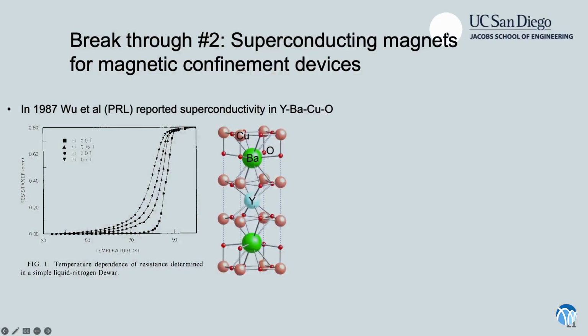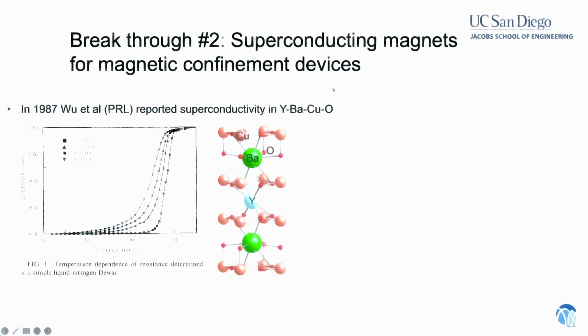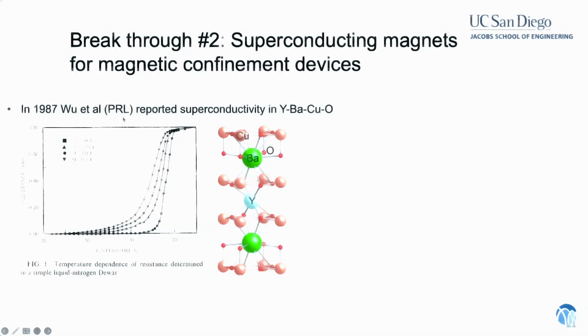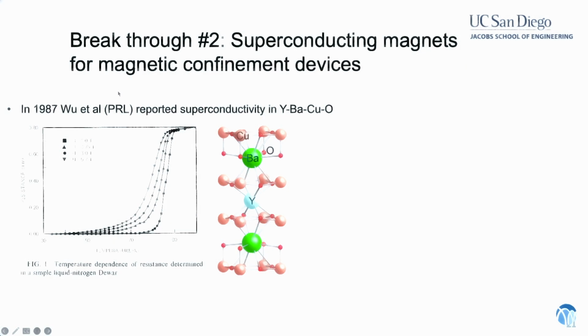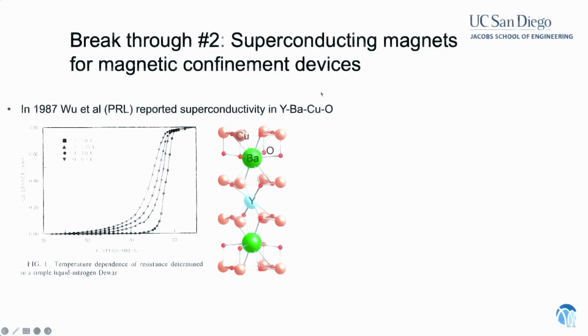The second breakthrough I want to talk about has to do with superconducting magnets for MFE, or magnetic confinement devices. This is some data out of a 1987 PRL paper by Wu et al. It's about high temperature superconductors. In this case, it was a mixture of yttrium, barium, copper oxide. On this plot, this is resistivity versus temperature. As you lower the temperature, the resistivity goes from pretty low to extremely low, and this is, of course, a transition to superconduction.